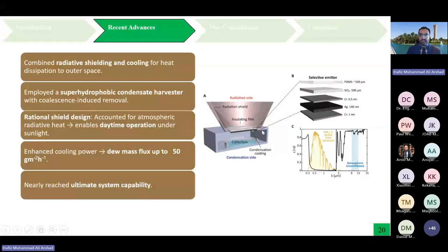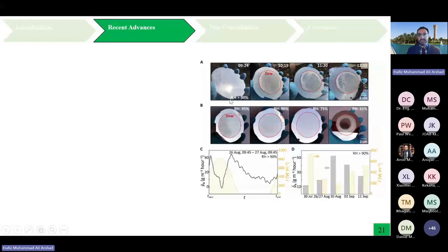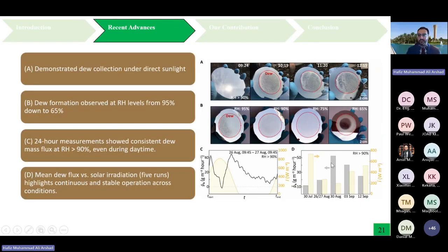Looking into that, when the relative humidity is more than 90%, during daytime they achieved dew, and even when the relative humidity was low, up to 65%, we can see that the dew is still there. And some of the tests reported on 30th August show that the water collection was up to 50 grams per meter square per hour.